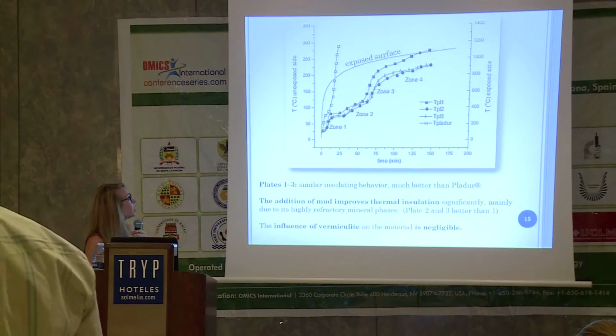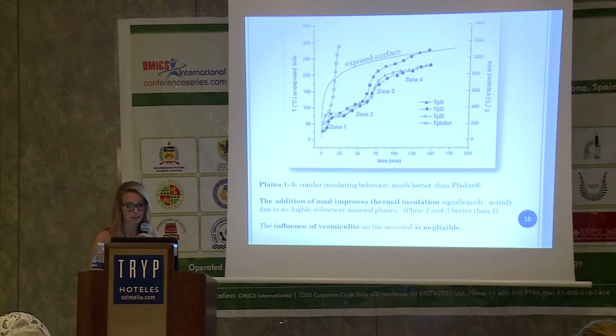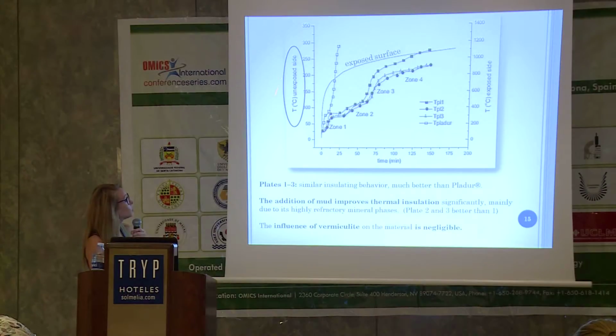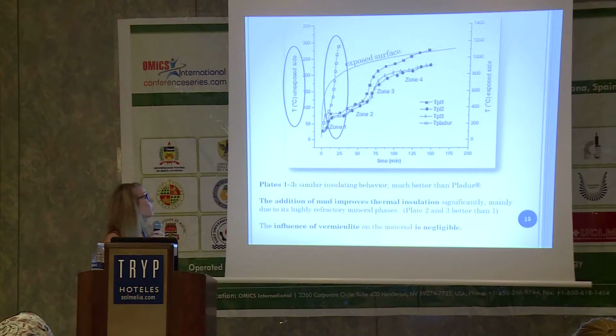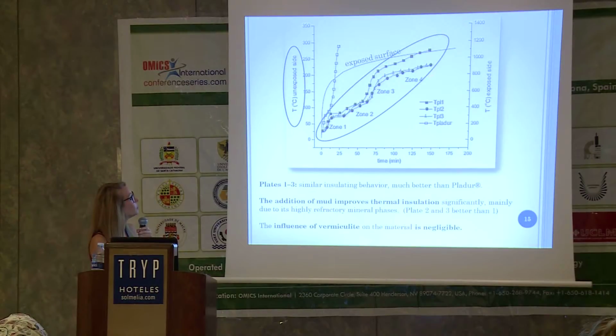In this figure the result is shown. On the right axis is represented the temperature on the exposed side, and on the left axis is the temperature on the unexposed side versus time. This line belongs to pladur, and you can see that it reaches high temperature in a short time, whereas the different plates need more time to reach the same temperature. So plates 1 and 3 have similar insulation behavior, much better than pladur.